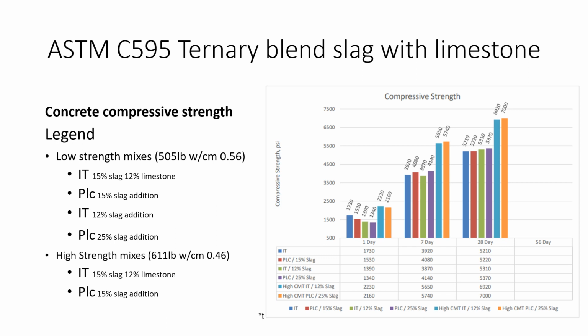Your water cement ratio seems to be on a higher end. Is that required? This is done in our testing. This is done deliberately. With the lower cement content mixes in our testing, what we're trying to do on our end is see the most change possible, right? So we're trying to dramatically make those changes in our mix design so that we can see, is there any variability happening in our system? That's the reason for that 505. The 611, if we do higher cement content mixes, we're not going to have as much difference in variability, is what we found.